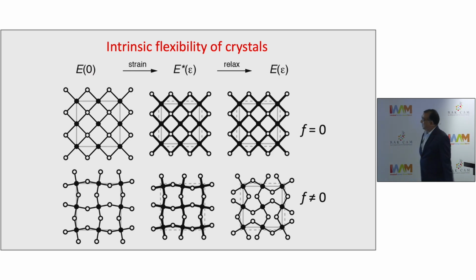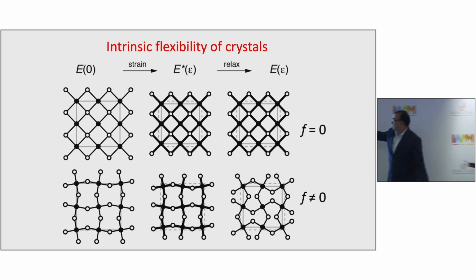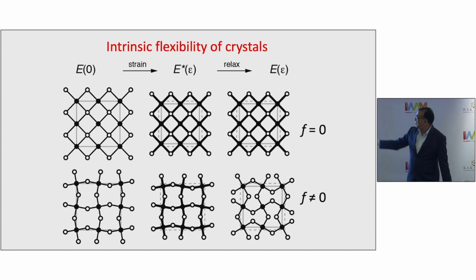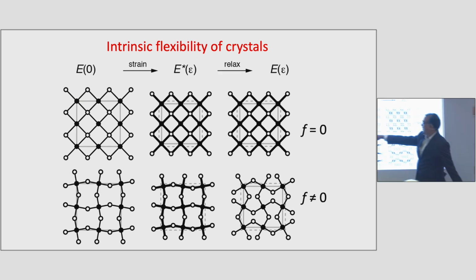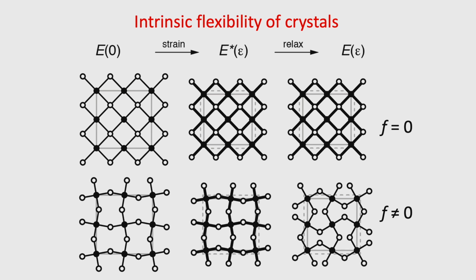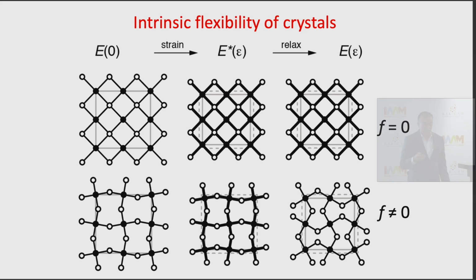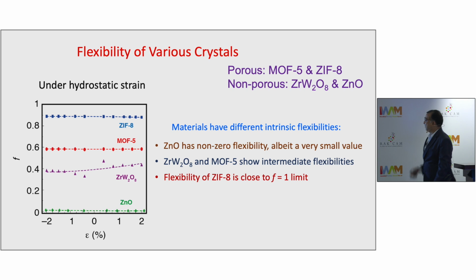Okay, so here is a pictorial view of it. The top panel shows that if I start with a crystal structure with 0 strain and apply a strain, this is the way that crystal will deform. And if I allow it to relax, it doesn't change its structure because there is no internal freedom. Whereas in the bottom figure, I start from this undeformed structure and deform it. It has room to adjust the buckling angle, and then it changes back to a relaxed state, and that has a non-zero flexibility. So that's the way we are looking at flexibility.